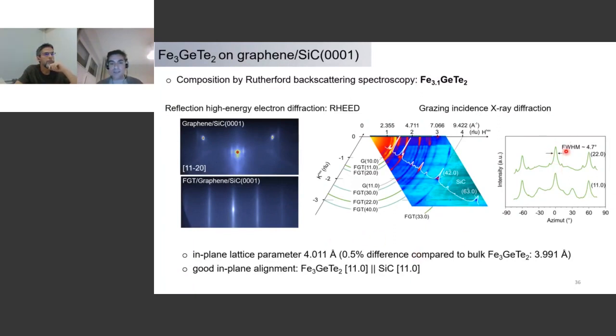We do have some mosaicity in plane. That means not all the islands that are formed and coalesce are epitaxially aligned in plane. We have some mosaicity, but in general, in terms of van der Waals epitaxy, we have a very good quality. Interestingly, though, you see that FGT is actually epitaxially aligned to the silicon carbide below, parallel to the silicon carbide.